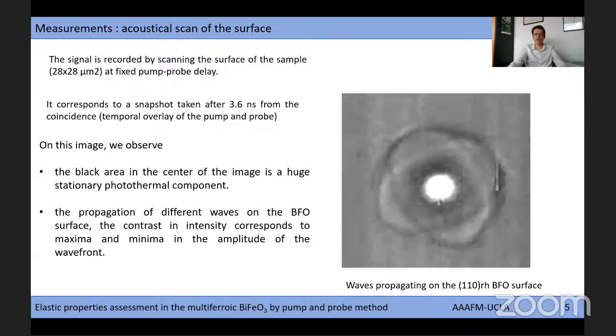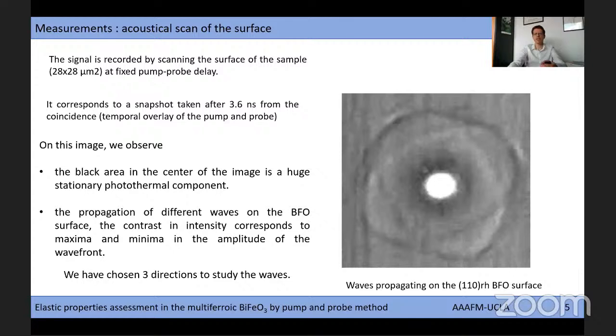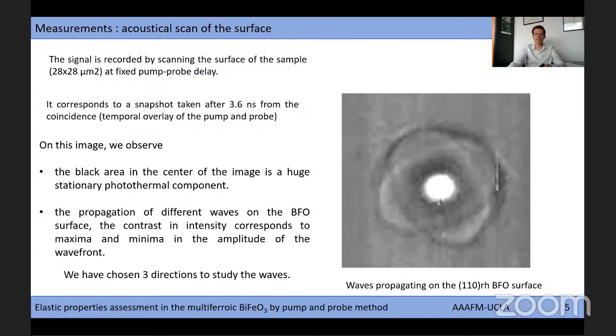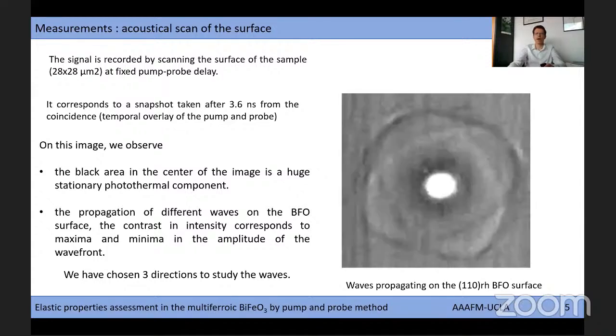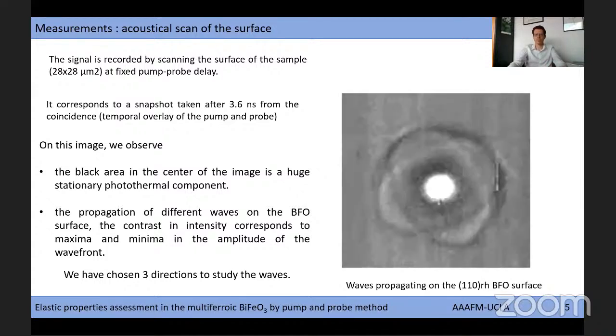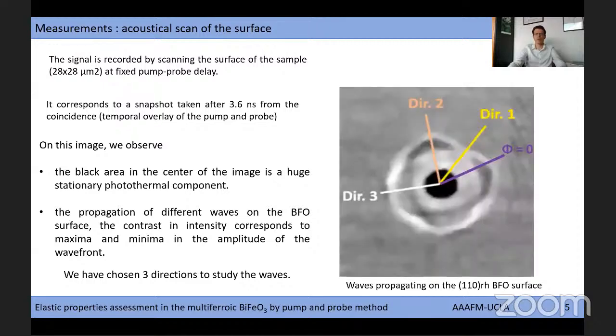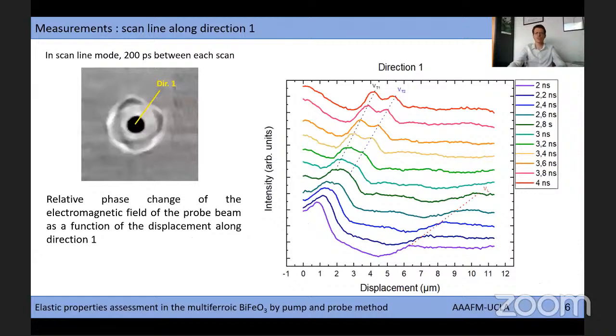We have performed scan lines along three independent directions to obtain the profile of the acoustic wave at different times of probe arrival after the coincidence. The next figure presents the relative phase change of the electromagnetic field of the probe along the scan direction 1 as a function of the probe position for several probe time delays. One can observe in this figure three peaks whose positions evolve as a function of the probe delay. These peaks correspond to wave amplitude maxima and three distinct propagation speeds.